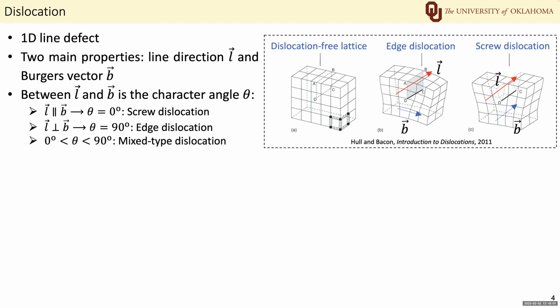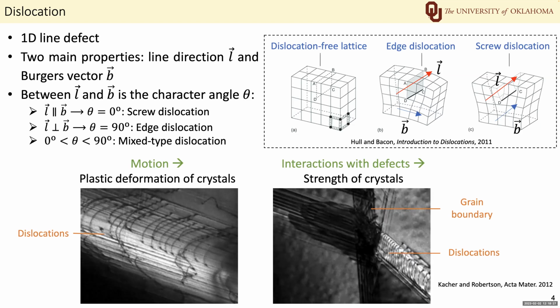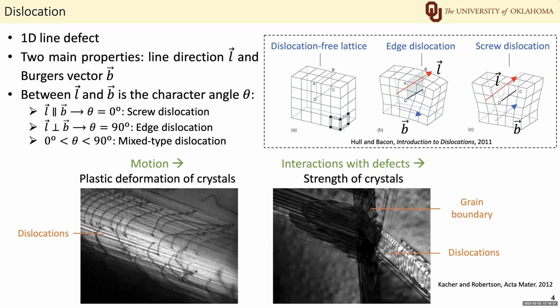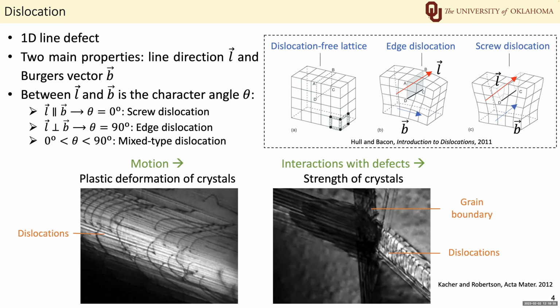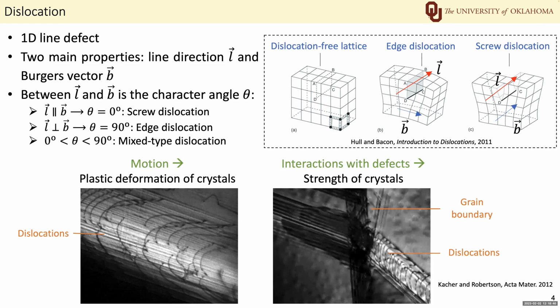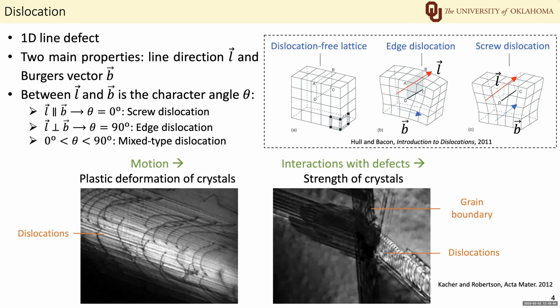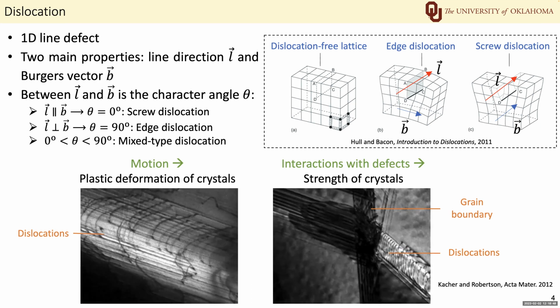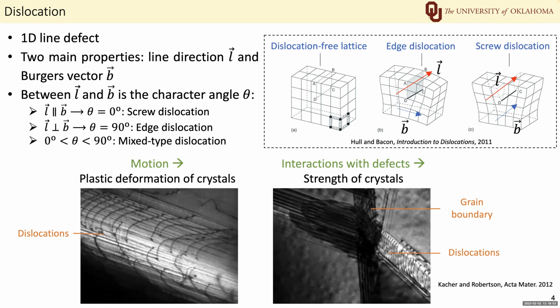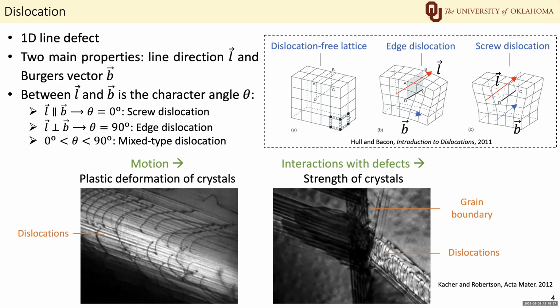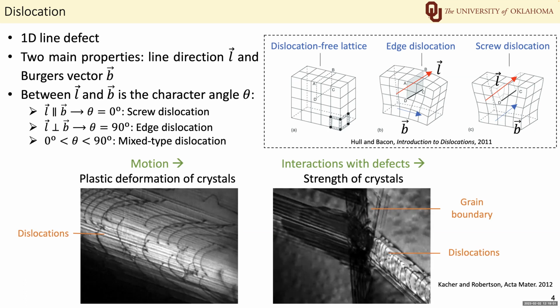When the angle is 0, it is a screw dislocation. When the angle is 90 degrees, it is an edge dislocation. When the angle is between 0 and 90 degrees, it is a mixed type dislocation. So the motion of the dislocation controls the plastic deformation of the crystal, and the interaction between the dislocation and the defect, such as the grain boundaries in the movie on the right, determine the strength of the crystal. That is why the dislocation plays a very important role in deformation and the failure of the ductile crystal.